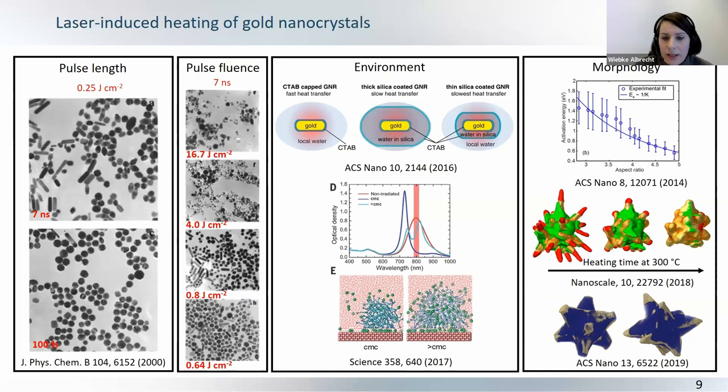And we've visualized that in the electron microscope, with electron tomography, very heated nanocrystals, and you could see here for this gold nanostar, that indeed these areas with very high curvatures, surface curvatures, deformed first. So, these red areas where atoms diffuse away, and they diffuse towards these green areas, which are areas of low curvature. So, we really have this driving force from high curvature to low curvature, and this we saw for different shapes.